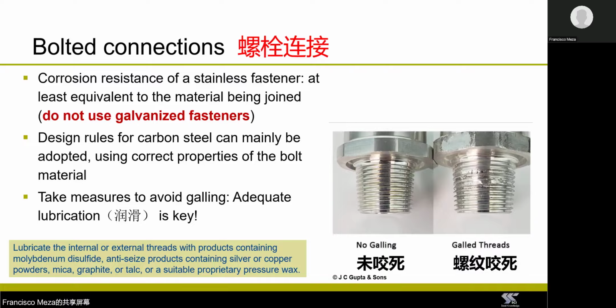Now, one thing you should be aware of when dealing with stainless steel bolted connections is that they are more susceptible to galling than carbon steel bolted connections. So galling might occur during the tightening of the bolt due to the relative movement between the threads of the bolt and the nut and the high contact pressures that originate. So this could result in the breakdown of the protective oxide layer of stainless steel. And if this occurs, it could lead to the threads of the bolt and the thread of the nut to bond together, increasing friction. And in extreme cases, it could lead to the threads of the bolt and the nut to fuse together, making it impossible to continue tightening the bolt or even removing the bolt.